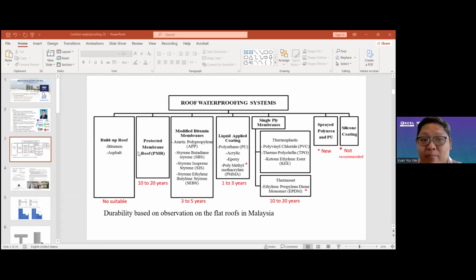another system known as protected membrane roof, whereby a layer of screed is put on top of the waterproofing in order to protect it against ultraviolet and heat. But somehow, this system worked very well. However, another group of manufacturers came up with another system known as torch membrane, or in America, modified bitumen membrane. It comes with different formulations, but again, manufacturers also discovered that it doesn't work very well. Another group of manufacturers came up with liquid applied coating using polyurethane, acrylic, epoxy, and even polymethyl methacrylate.